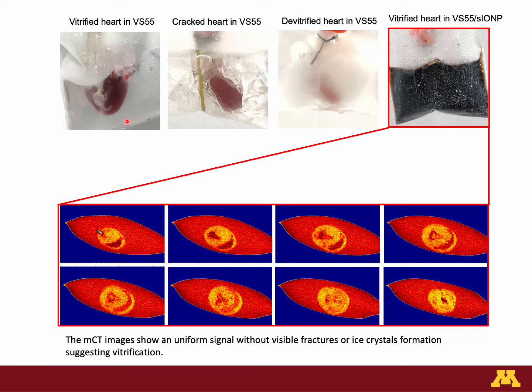Here you can see photos of vitrified, cracked, and devitrified hearts in VS55, and a vitrified heart in VS55 and silica-coated iron oxide nanoparticles. Cryobags containing vitrified hearts in CPA solutions are clear with the heart visible, and cracked and devitrified hearts were easily identifiable. However, for successfully vitrified hearts in VS55/sIONP solution, we were unable to visually examine the state of the interior of the bag. Therefore, we used micro-CT to look inside the vitrified sample. The micro-CT images show a uniform signal without visible fractures or ice crystal formation, suggesting vitrification.